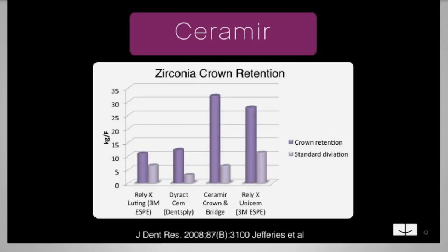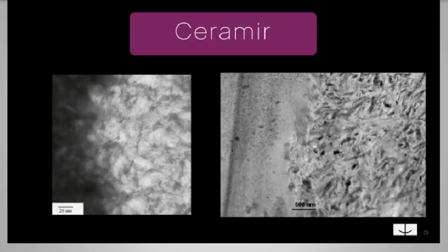For zirconia, now because of the phosphates, remember, right? Phosphate groups in zirconia. That's why Ceramir bonds so well to it. So you can get really, really high bond strengths to the zirconia. But again, if it's not retentive, then I still wouldn't use it. But it bonds very well to zirconia because of the phosphate groups. Now here are images of crystalline nanocrystal particle formation. You can see between the tooth and the substrate, you have these crystals formed.